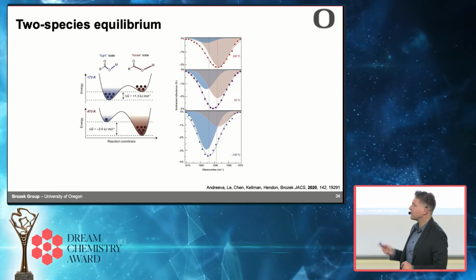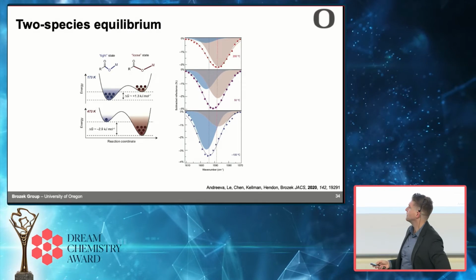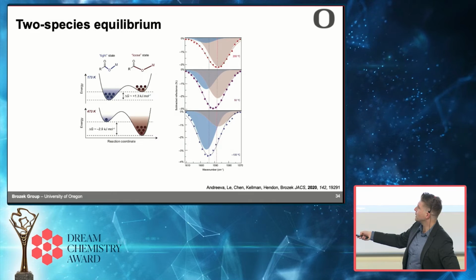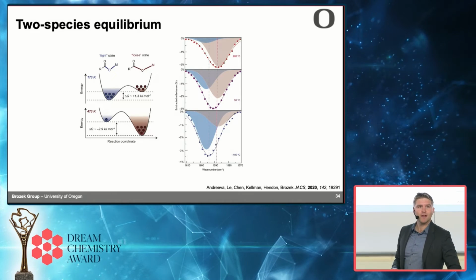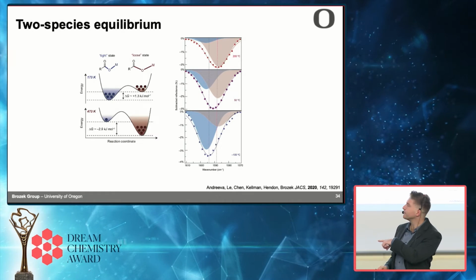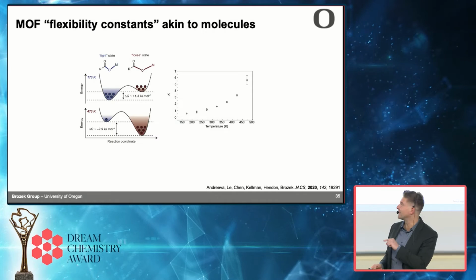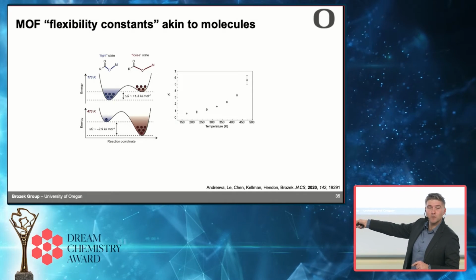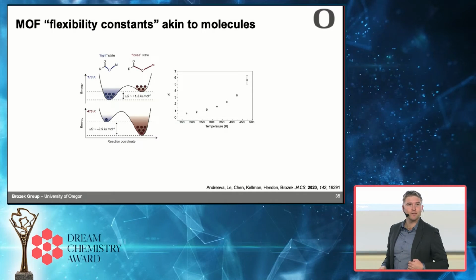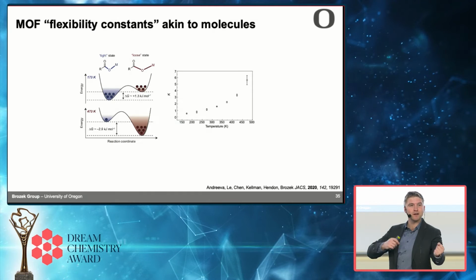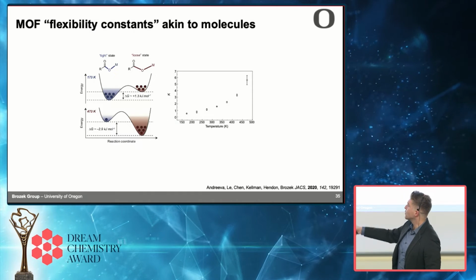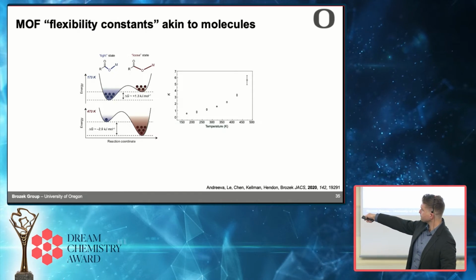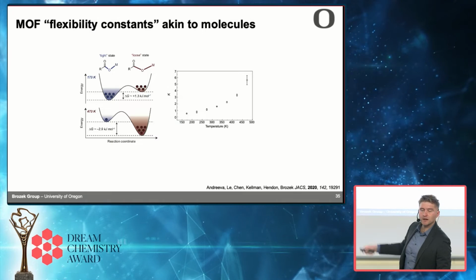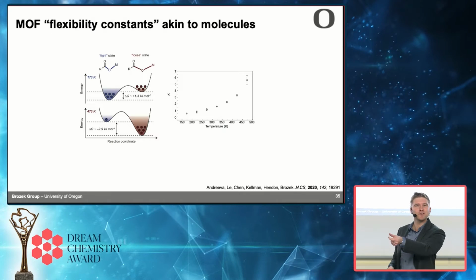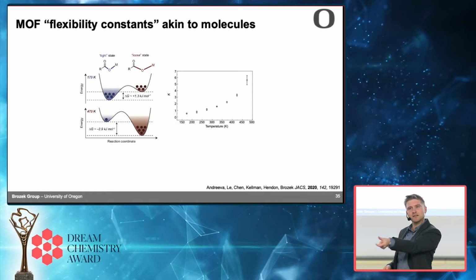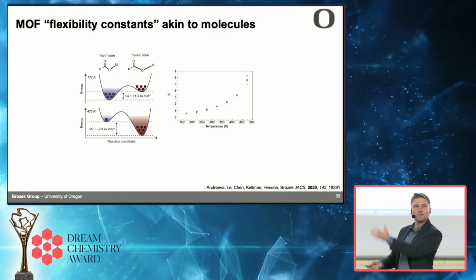Okay? But the other nice thing about doing this fit is that you can integrate under these peaks. And if you take the ratio of those two, there's a lot of information hiding in there. That gives us the equilibrium constant of this process, of the MOF bonds being bound and unbound. Okay? And so we can plot that equilibrium constant, and we see it increases as you heat up the material. This is the inverse of, if you're familiar with stability constants, this is the inverse. So bigger K means more of the unbound.